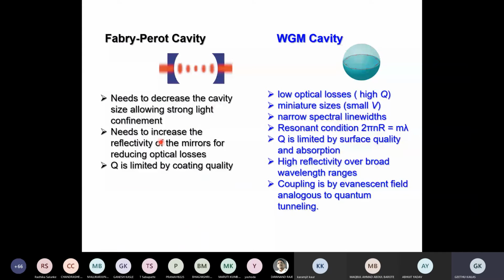Just have a comparison between the Fabry-Perot and WGM cavity. The Fabry-Perot cavity needs to decrease the cavity size for strong light confinement and frequency selection. It needs to increase the reflectivity of the mirrors for reducing the optical losses. Q is limited by coating quality. But in WGM cavity, low optical losses. It has high Q. Miniature sizes are very much possible. You can create micron sized or polymer beads very easily. Spectral widths are very narrow.